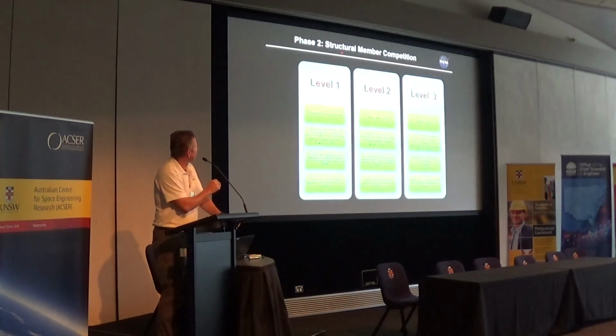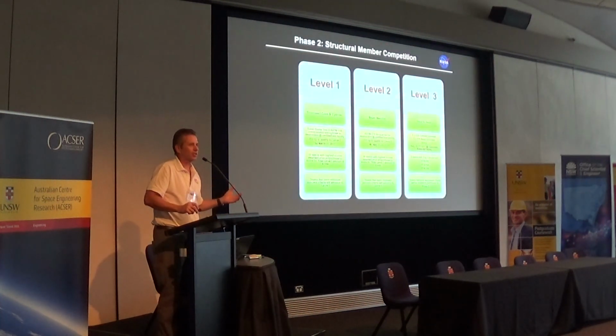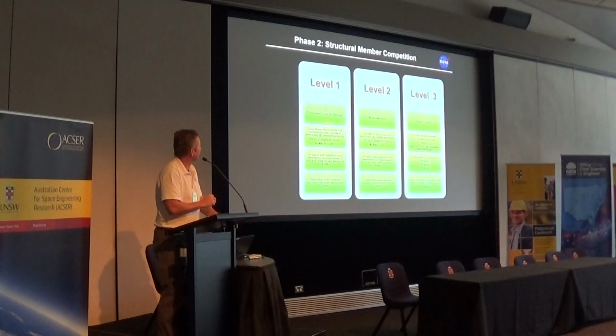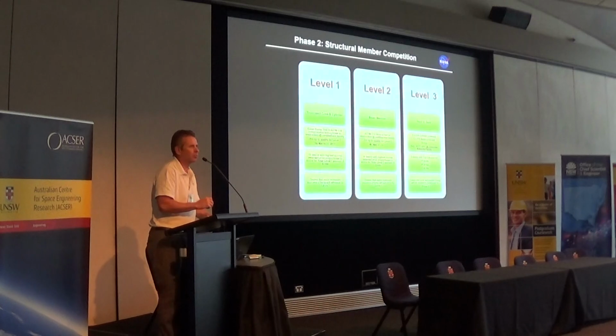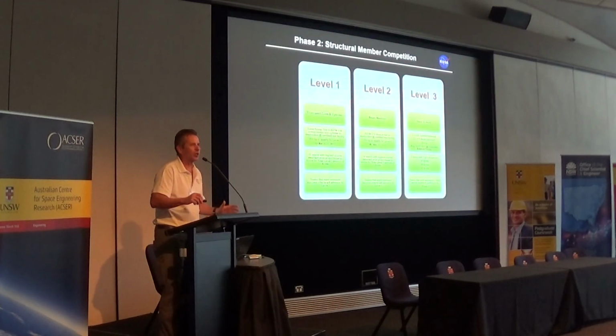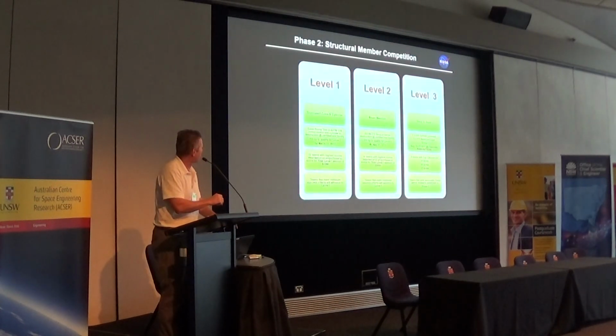Phase 1 was the architectural design. Phase 2 was to develop the new material, the material that you 3D print with. We call it the structural member competition because first they 3D print a truncated cone and cylinder and test that, then they print a beam and test it in 3-point bending. Then we have a head-to-head competition, which we just had 3 weeks ago in Peoria, Illinois at the Caterpillar facilities, and they actually had to 3D print a 1.5 meter diameter dome.